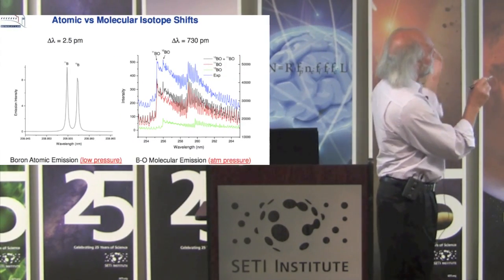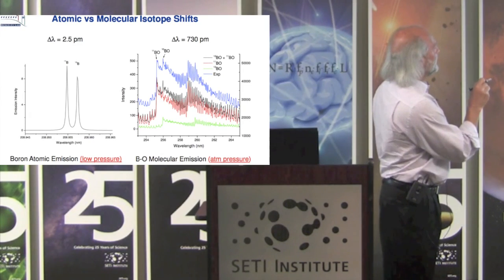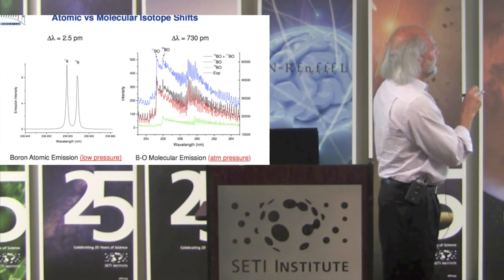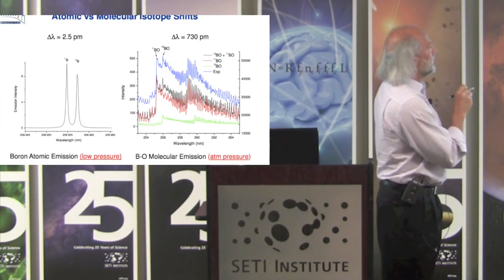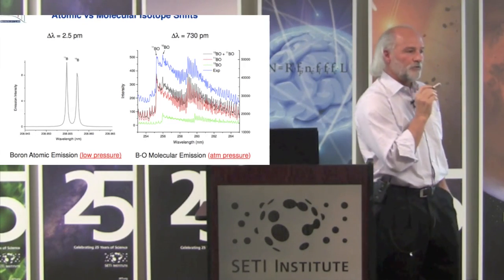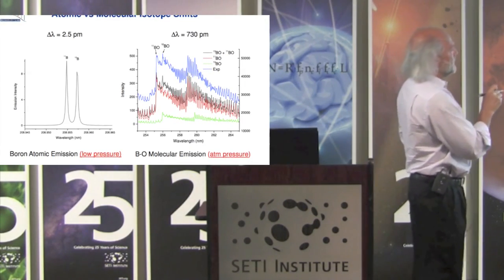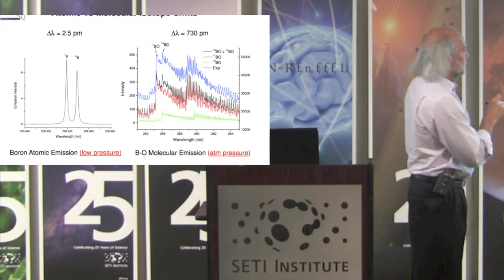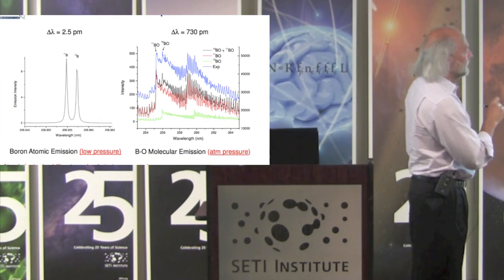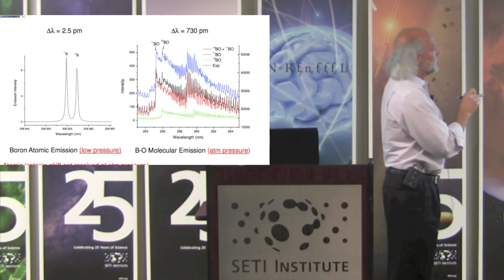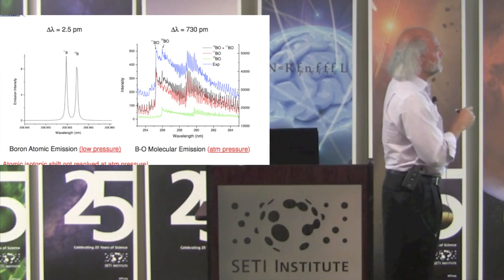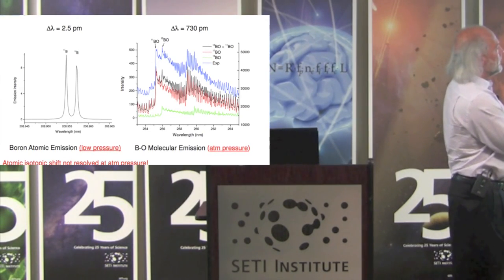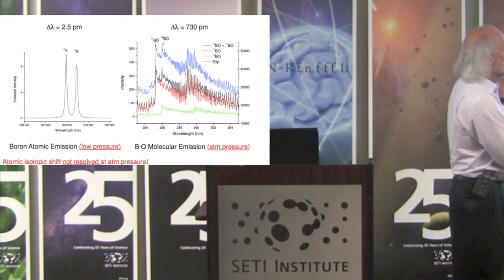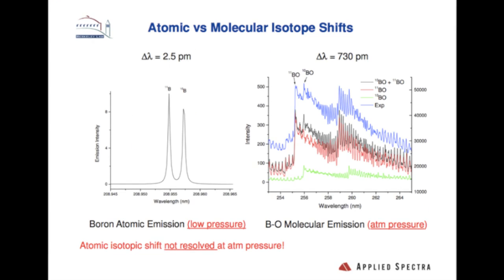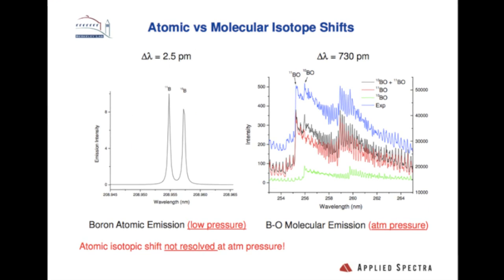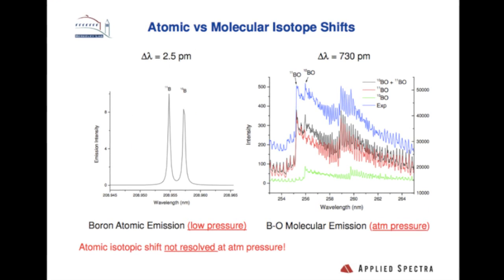Okay, so I could add or subtract. It's 2.5 picometers. So in order to see this boron atomic isotope splitting, boron-10, 11, you would need a very low pressure plasma, and you would need a very high resolving power monochromator. We're looking at the boron-10, boron-11 splitting at atmospheric pressure with a very low resolving monochromator.